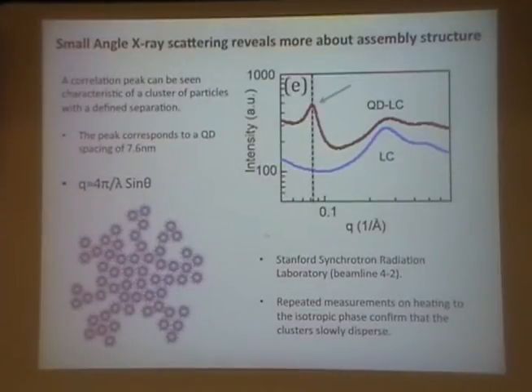Another thing that we can do. So, do you know the reason why they are diffused out in the isotropic phase, the aggregation? Well, yes, because in the nematic phase they form clusters to minimize the impact on the nematic phase. Right, so we don't want to have many small defects everywhere. They cluster together to create one defect, one deformation. Yes, so it's a lower energy cost. When you go back to isotropic, that removes the impact of that energy cost.